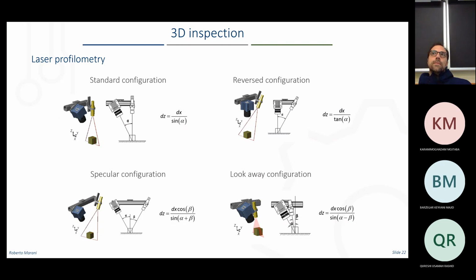The problem is that when you work with specular configuration, you can get multiple reflections. So this condition that I told you before, that there's just one line in your camera, could not be valid at all, because maybe there's another reflection here, multiple reflection due to the structure. And this is very important when you work with metal surfaces. So if you extract this column, here you get a maximum reflection of 255 of intensity. And this point, for example, is lower. Your intensity is about 180. I mean, the value of the pixel in that position.